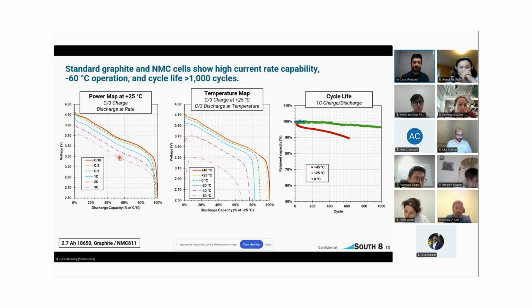And you can see our liquefied gas electrolyte can handle these increased rates without any problem, still achieving close to 100% discharge capacity at those higher rates. You can always expect a little bit of voltage drop there with the electrical impedance and things like this. On the temperature map, we are charging these cells at C/3 at room temperature, but then discharging across all these temperatures. So everything from 40 degrees Celsius down to minus 60 degrees Celsius, we're operating very well in.